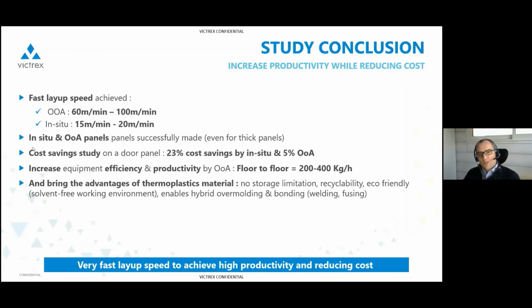That was not the objective of this presentation, so we can maybe take this offline if more information is needed. But we can say, okay, it's great to go fast, but so what? We also ran some studies to quantify, because that's a key driver to address the cost savings. Based on a very specific case, a door panel, we looked at the cost savings by in-situ and out-of-autoclave, and we ended up with significant cost savings for in-situ, close to 23%. That's mainly because you don't have any consumables, as you know. And for out-of-autoclave, it was only 5%, because the part was maybe too small to take advantage of the high speed, but also maybe the volume. That tells us that you need to choose the right manufacturing process for the right part.